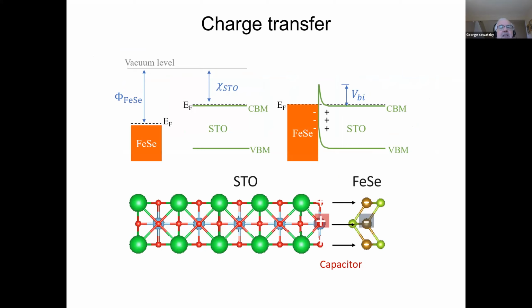I do want to mention this. So if the material is doped, then of course, you have taken electrons from STO because the STO had extra electrons in it at the bottom of the d band. Okay, so they're over here. The Fermi energy for STO would be up over here, and there are electrons in the conduction band, the titanium d band of STO, because of the niobium doping or oxygen vacancies. And the work function there is actually lower than the work function in iron selenide. And that means, as I show on the left-hand side here, that those electrons will flow as much as possible to the iron selenide.